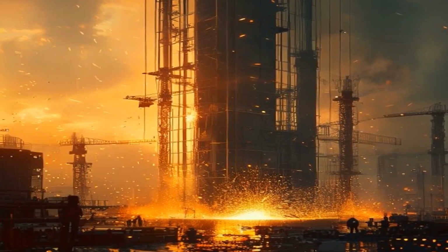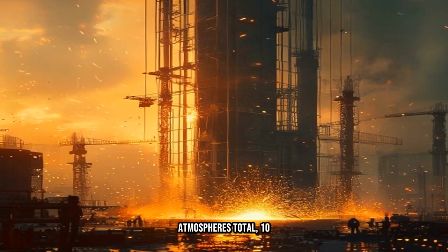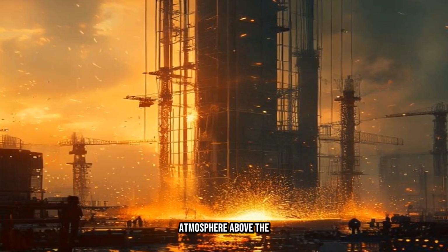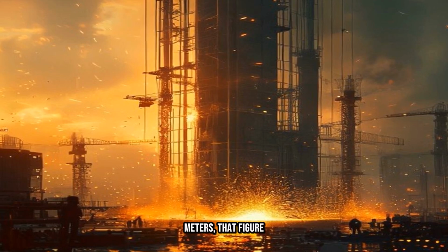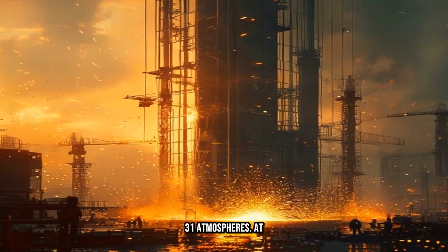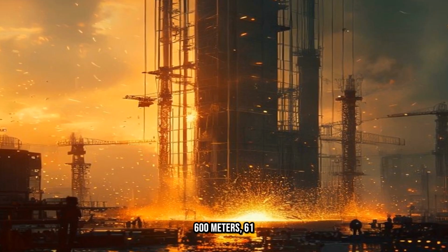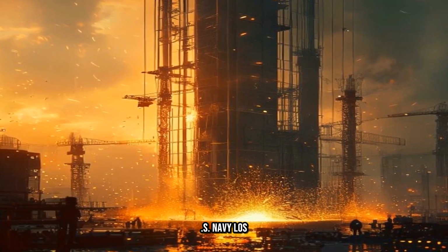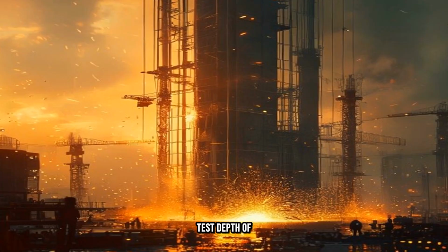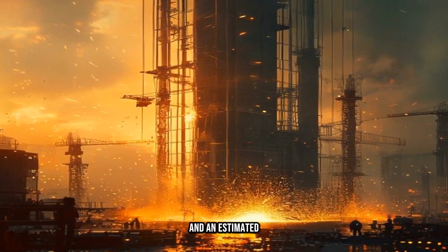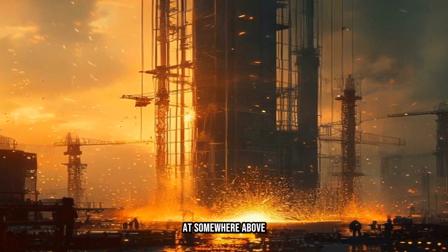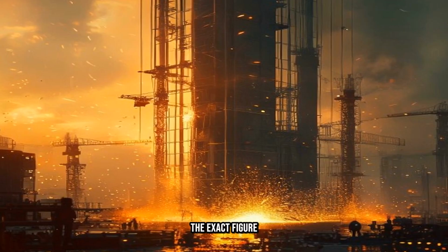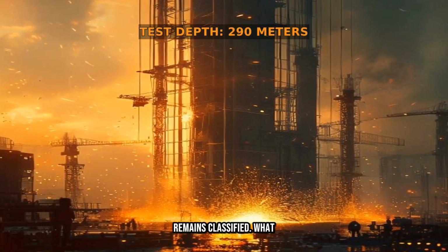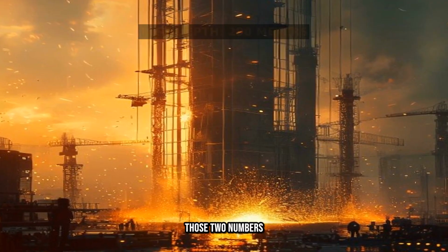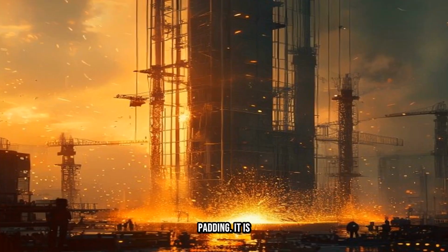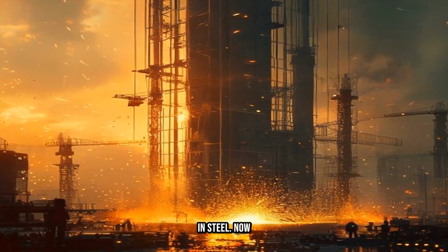At 100 meters, you are dealing with roughly 11 atmospheres total, 10 from the water, 1 from the atmosphere above the surface. At 300 meters, that figure is closer to 31 atmospheres. At 600 meters, 61 atmospheres. A U.S. Navy Los Angeles-class submarine has an official test depth of roughly 290 meters and an estimated collapse depth that naval architects place at somewhere above 730 meters, though the exact figure remains classified. What matters for our purposes is that the gap between those two numbers is not comfortable padding. It is engineered geometry, expressed in steel.